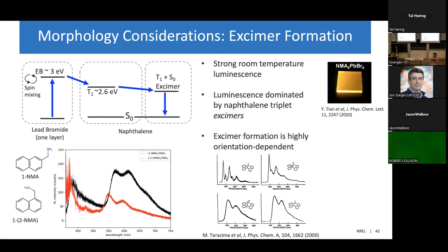Now, excimer formation is highly orientation dependent. So here I've pulled a figure from a work where the authors looked at a series of L-shaped naphthalene dimers. And depending on the rigidity of the dimer and the tilt angle between the chromophores, you see a transition in the photoluminescence from the monomeric behavior, which are the spiky spectra at the top, to the broad excimeric emissions that you see at the bottom, all right? So there are a lot of morphology considerations here when it comes to what's dominating the luminescence of your films.